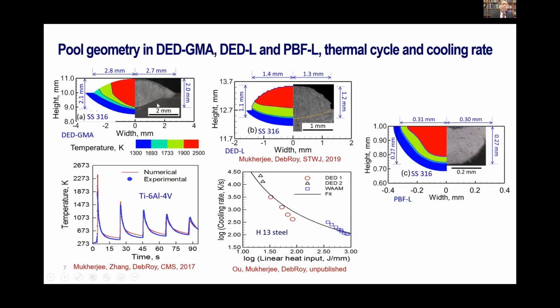And here I am showing the pool geometries computed for directed energy deposition GMA that gives us a very high rate, directed energy laser that feeds metal powders coaxial with the laser beam, and thermal cycles and cooling rates are also outputs from the model. So if you compare the GMA, you will see that the pool half width is about 2.8 millimeters. Whereas if you go for powder bed fusion, the pool half width is only 1/3 of a millimeter. So it's a much smaller pool.